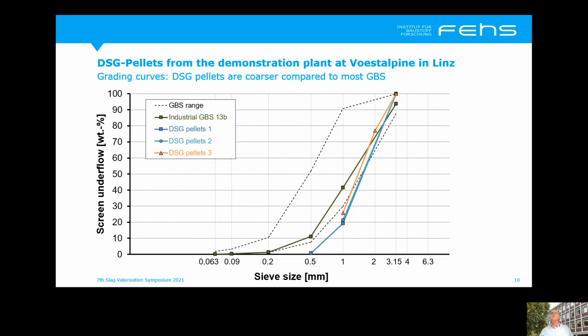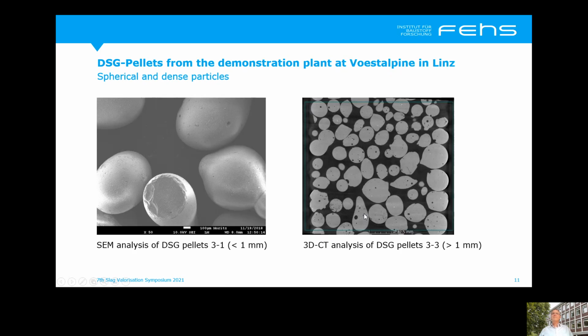Looking at the grading curves, the DSG pellets are coarser compared to most GBS, and also compared to the wet granulated GBS 13B from Linz. That is very important for the later discussion. The particles are spherical and very dense, as you can see here in the SEM picture and 3D CT analysis picture.